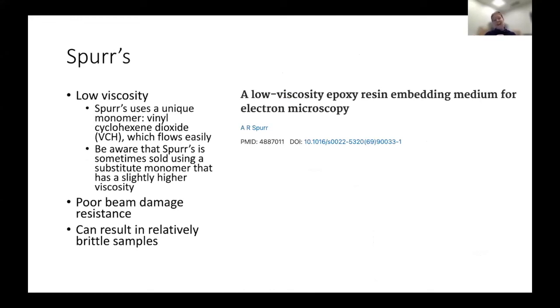SPURR's is also, okay, we should also have SPURR's. SPURR's is, as far as I know, one of the lowest viscosity resins. It can infiltrate dense samples very well and also large samples very well. There's an interesting history about this resin because the monomer that was originally published, which is a low viscosity, is generally not included. When you buy a SPURR's kit, it's often a SPURR's substitute. And after having compared the two monomers, I can say definitively, the original monomer is substantially lower in viscosity than the substitute, which I find really interesting.